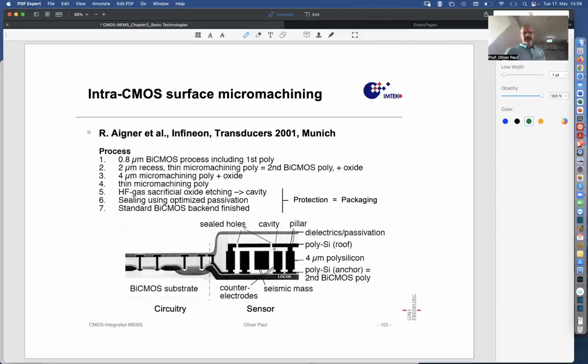And so anyway, Infineon, another highly stratified company, presented many interesting results at that conference. And here is an example of intra-CMOS. So you can imagine that the CMOS was performed until about this layer here. So that's what came before. And then, that's up to polysilicon. So polysilicon is 650 degrees or so. So if you have a deposition process for the thick polysilicon on the right that does not exceed the temperature or remains even below, then you're safe. So that's what they did.